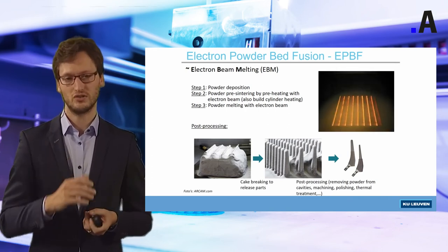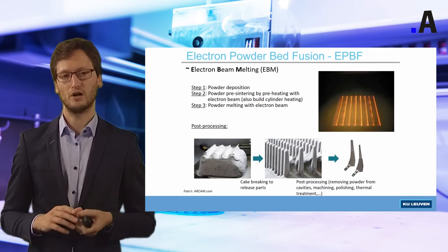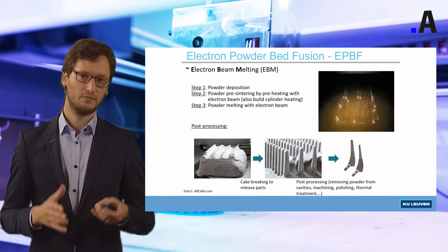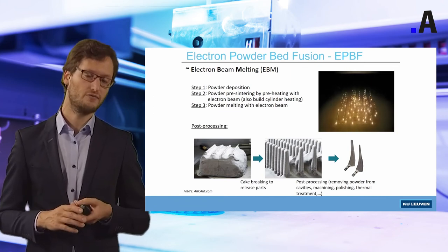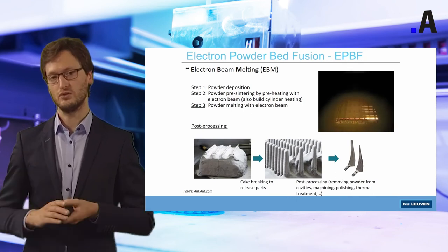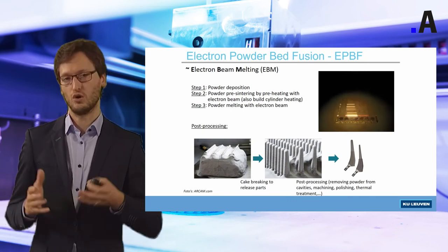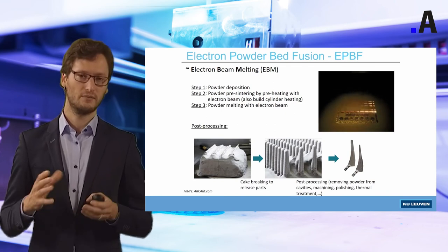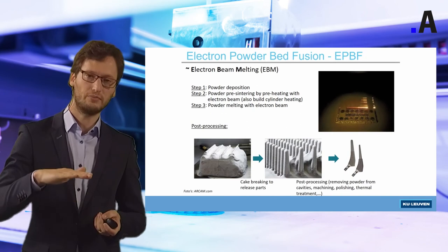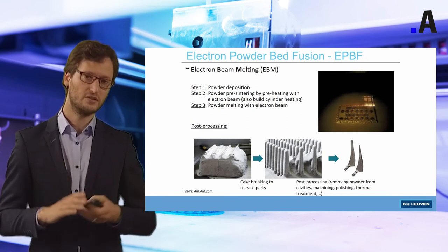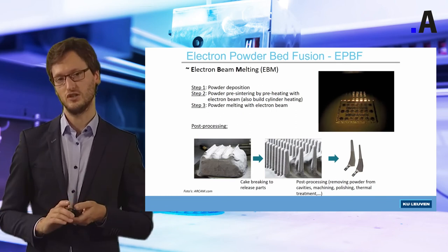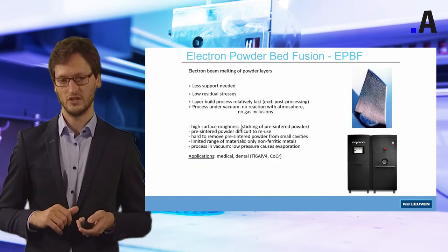In many cases, as you can see with this hip implant part, post-processing technologies are needed. However, the pre-sintering also has advantages. Typically you do not need support structure, or at least less than for SLM, because sintered powder can carry the load. Also, because of the preheating, the thermal gradients during printing are less pronounced, so deformation and residual stresses are lower.